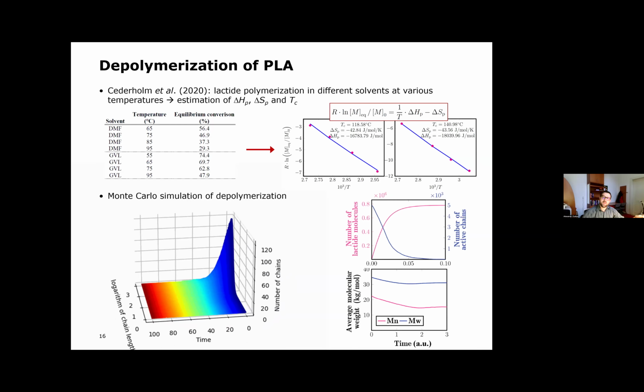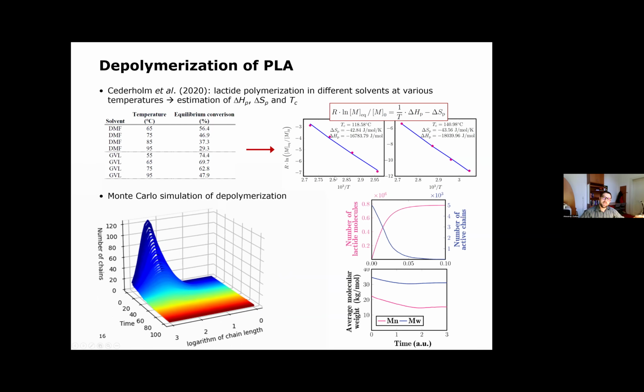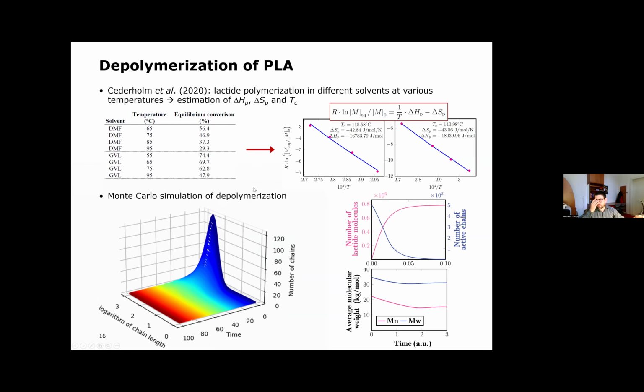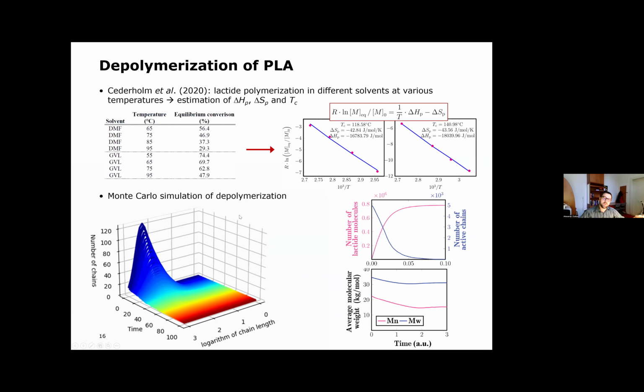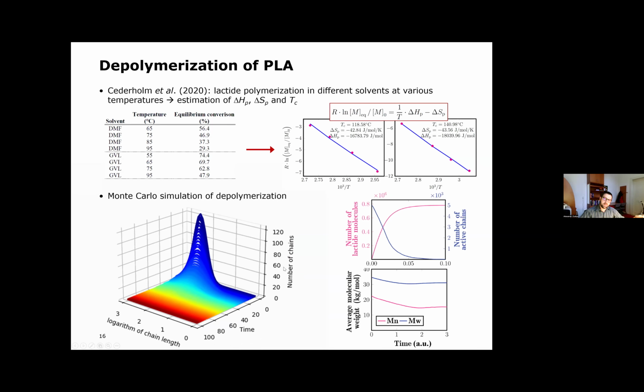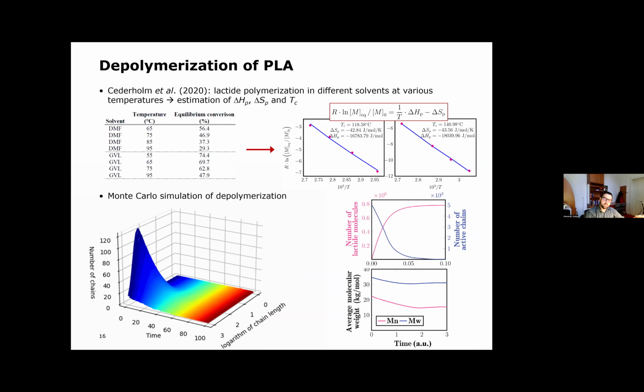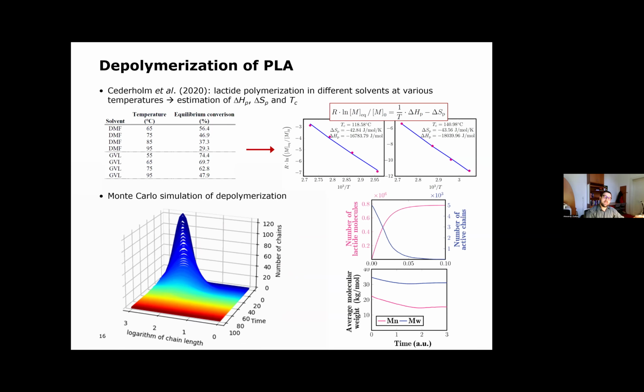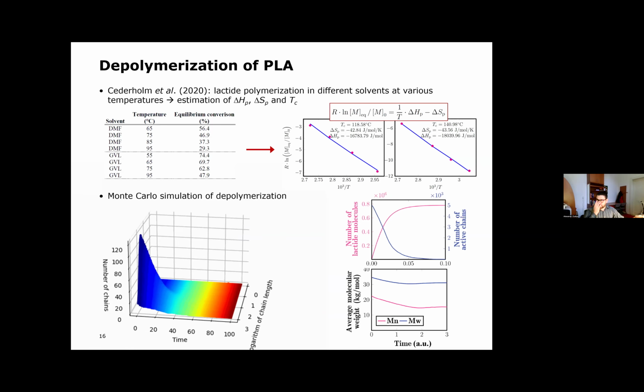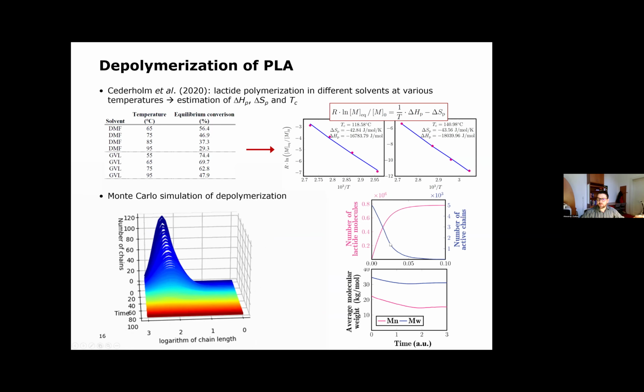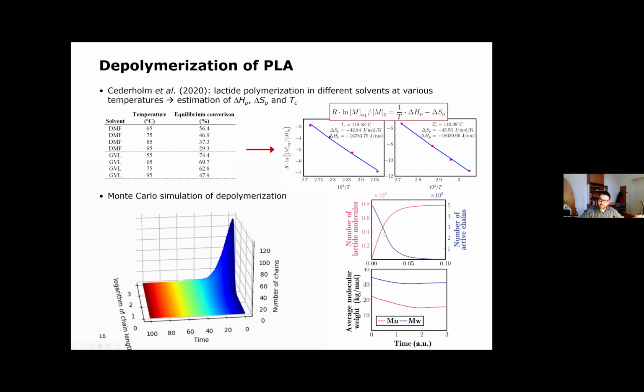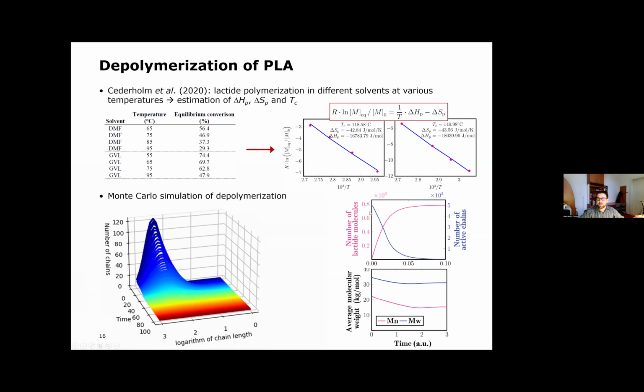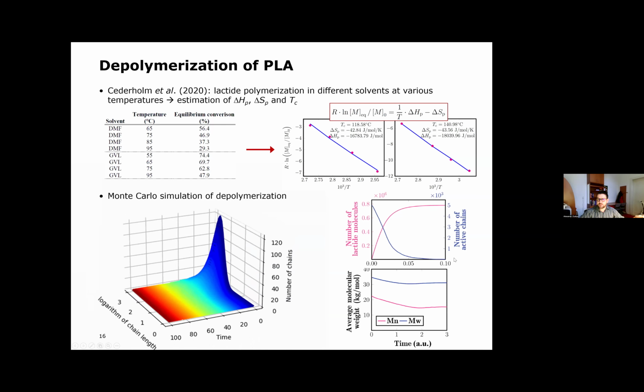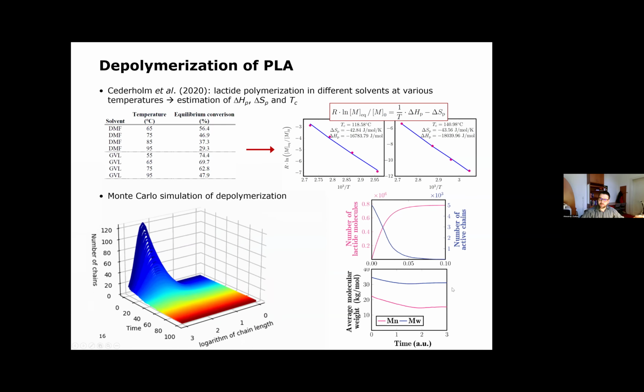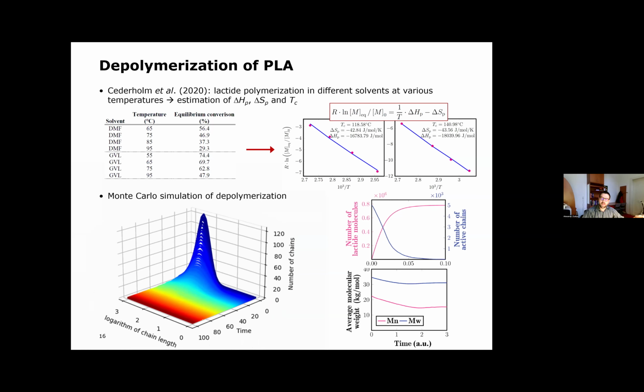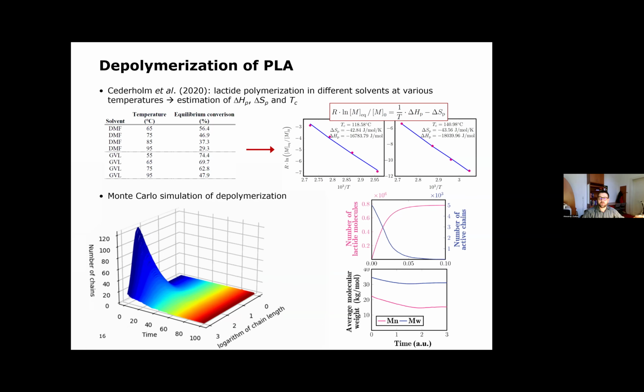So we are able now to process this data to estimate these properties of the polymerization, which we can then use as input parameters to our Monte Carlo models. And here in this rotating plot, you see one example of a simulation of how the evolution of the molecular weight distribution is changing over time when you depolymerize. And the same is translated here in the right part of the graph. The number of lactide molecules, which is the monomer, is increasing over time, while the number of polymer chains is decreasing. And here is the information about the average number and weight average molecular weight of the polymer during the depolymerization.